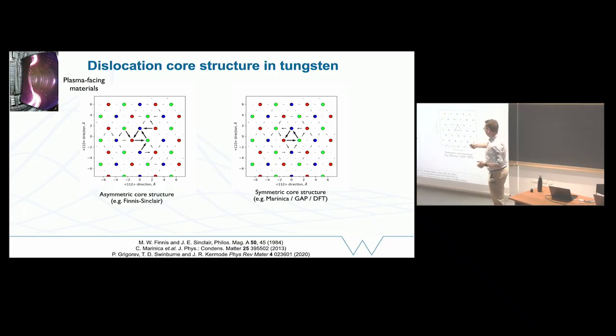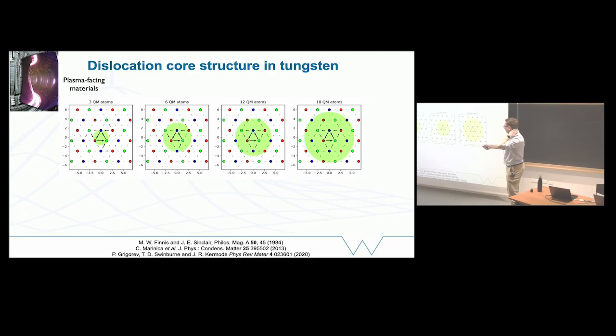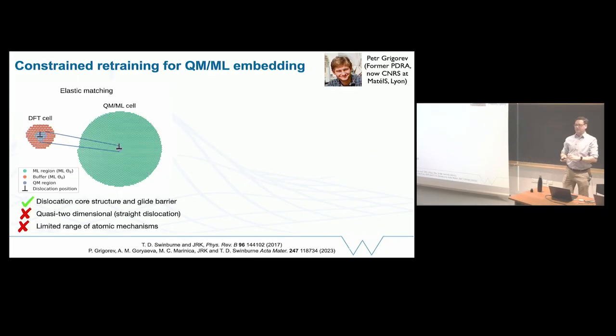And what you can see really is that this one is wrong. It doesn't have good symmetry. It should look more like this, where you have a nice compact core and then everything lines up well. And this is what you get with either a very good embedded atom potential from Cosmin Marinica in CEA or a machine learning potential. And you don't actually need to treat very much of the system with an accurate model in order to fix that asymmetry that you're getting from the simplified model. So this is a good example, but it comes back to the question about 2D versus 3D.